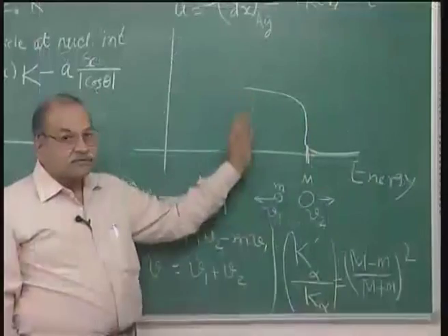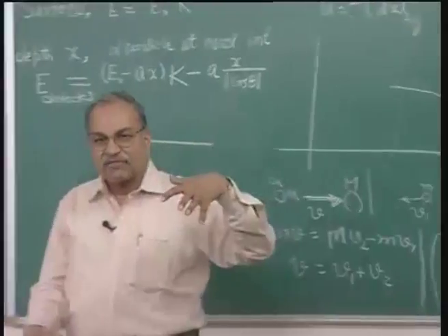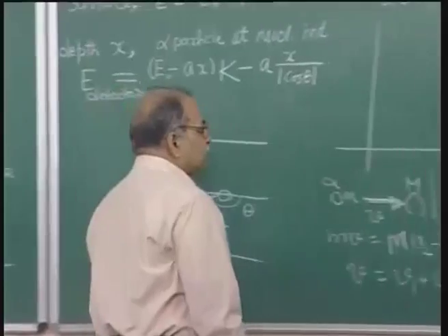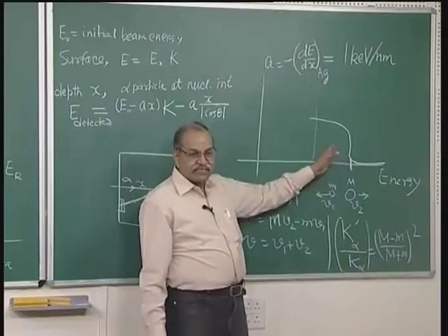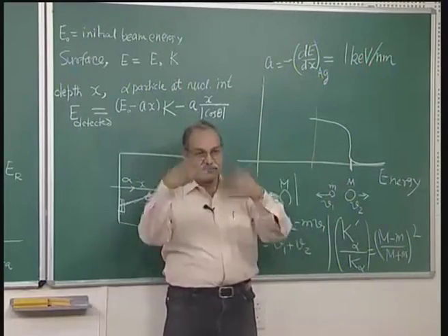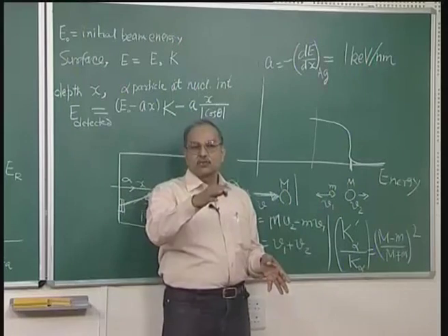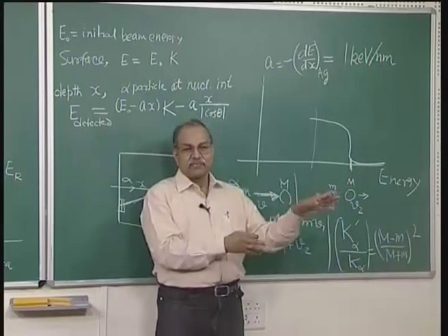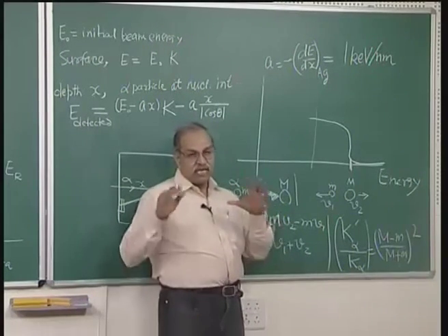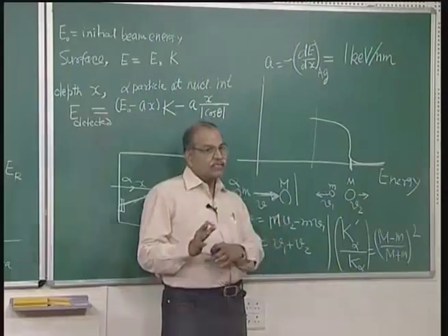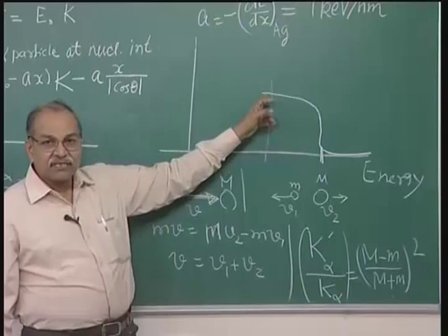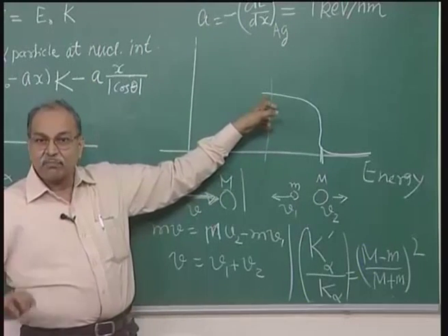And then this height depends on how many counts I am receiving, which depends on the cross section and other things. Normally, cross section decreases when energy is increased. If you remember the Rutherford equation, the energy comes in the denominator with Z1 Z2 divided by some epsilon naught etc., and the whole thing is squared. So, with the same concentration, lower energy will have a larger cross section and counts will be larger. That is why it is slightly going up.